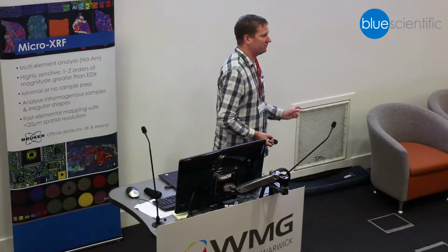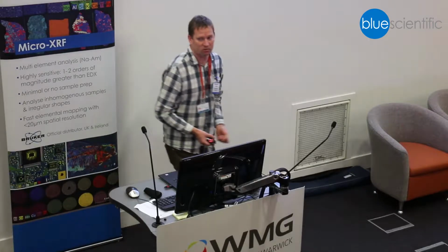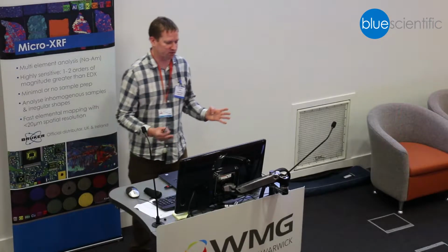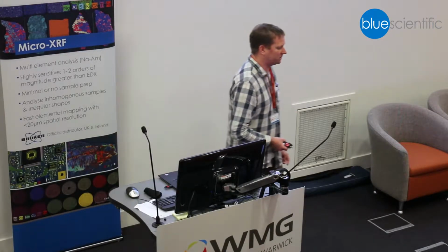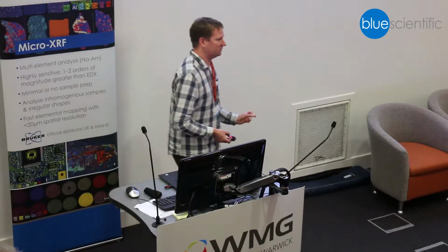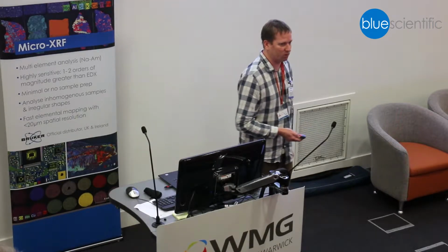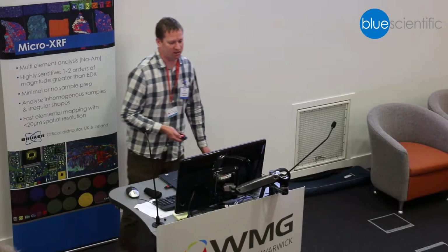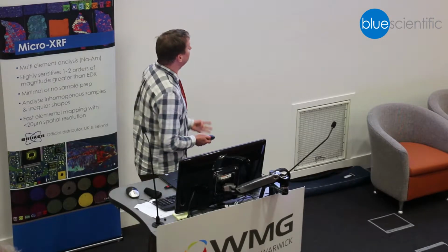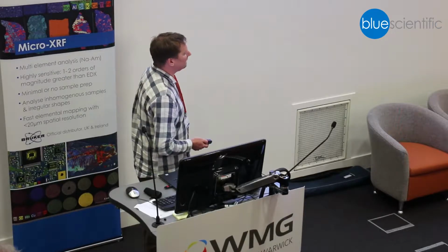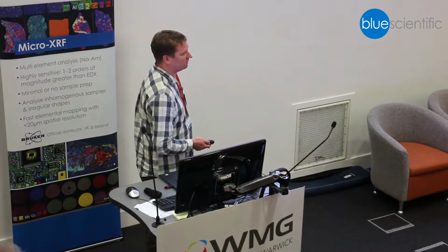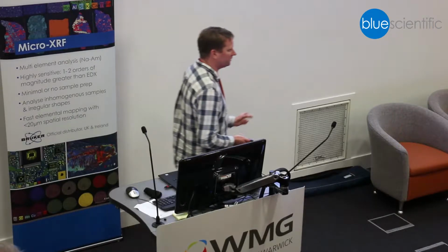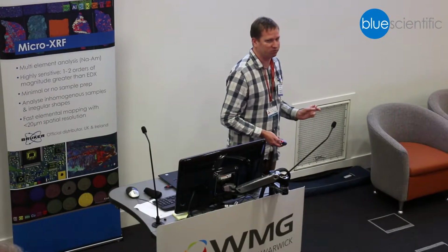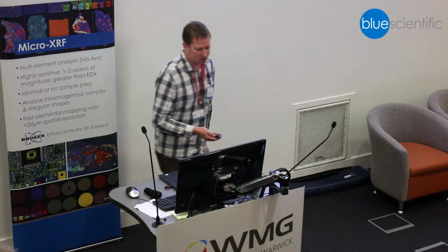We're also interested in how the quantification we got from the XRF would correlate to what we're more used to in the SEM. So based on this map showing the compositions in XRF, we were then able to go into these areas and do EDS in the SEM just to get sanity on how close we were with the techniques. And what we see is that we were very happy with how close we were in all the areas we analysed. Obviously, with the caveat that Micro-XRF doesn't tend to perform brilliantly at the light element range.